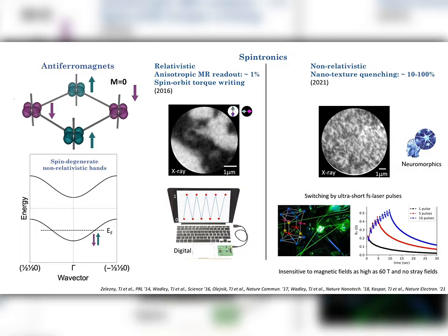And finally, because these are antiferromagnetic devices, they are, unlike ferromagnets, highly insensitive to magnetic field perturbations. And in these particular switching concepts, it's been demonstrated that even a 60 Tesla field is not disturbing the functionality of such an antiferromagnetic device.